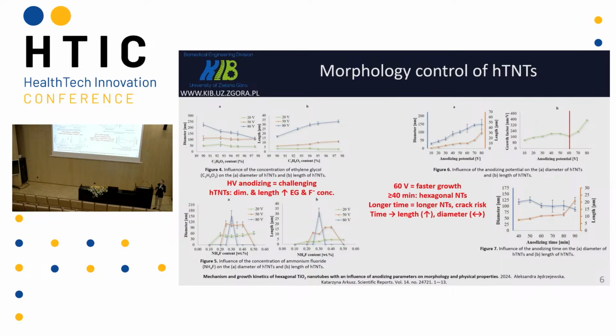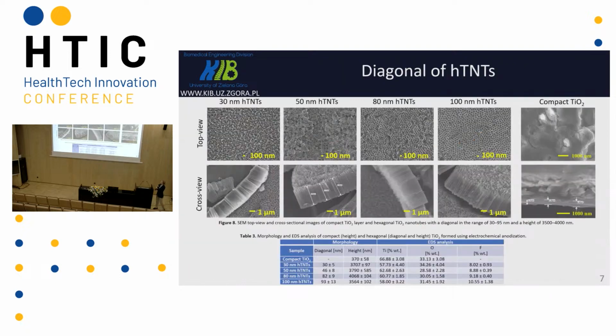So the diameter depends on the voltage during the anodizing process, and the length of this layer depends on the time. But when we use high voltage anodization, this process is completely changed. Another key aspect is the concentration of fluoride ions and the concentration of ethylene glycol used in the electrolyte. So as you can see in this picture, there's a very small range of this concentration which allows us to form hexagonal titanium dioxide nanotubes.